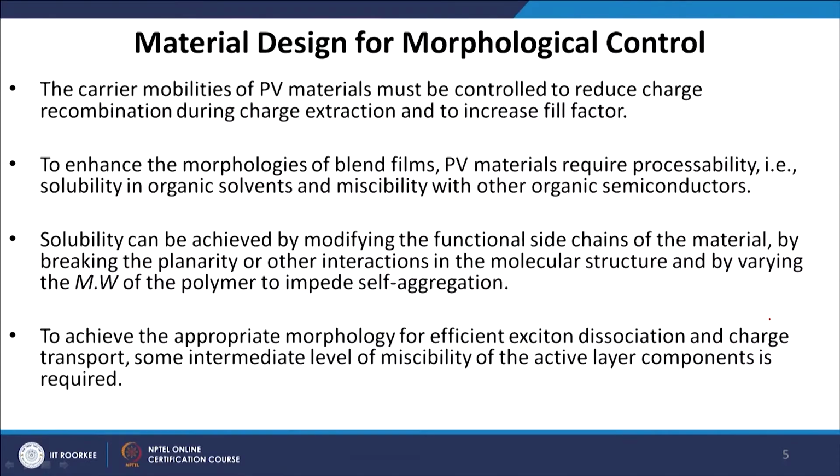So, that is why solubility is very important, and whatever material you have designed should also mix well with the acceptor material. So, miscibility is also an important parameter. Solubility can be achieved by modifying the functional side chains of the material, by breaking the planarity or other interactions in the molecular structure, and by varying the molecular weight of the polymer to impede self aggregation.